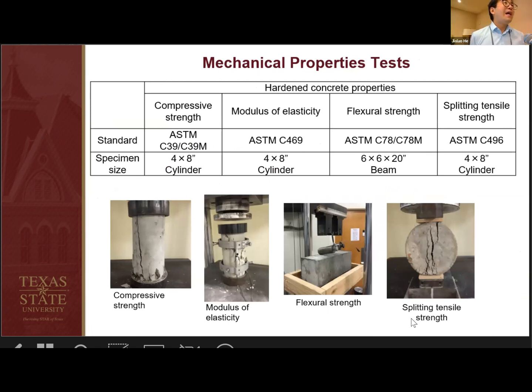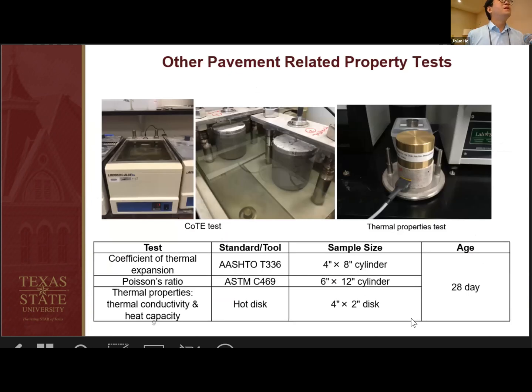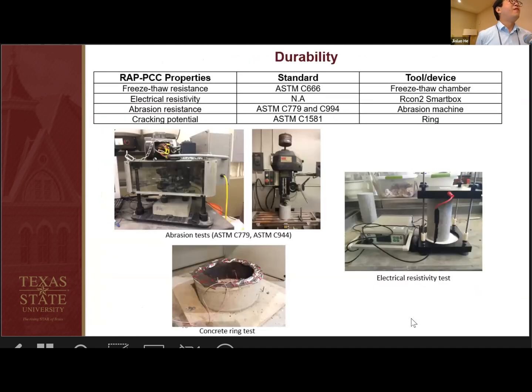Then we did a lot of mechanical property tests: compressive strength, modulus of elasticity, flexural strength, and split tensile strength. We also did some pavement-related property tests because our goal was to design RAP concrete for pavement applications in Texas. So we did coefficient of thermal expansion, Poisson's ratio, and some thermal property tests. We then evaluated the durability of concrete made with RAP aggregate. We did freeze-thaw resistance, electrical resistivity to infer the permeability of the concrete, and abrasion resistance. We also did a ring test to look at the cracking potential.